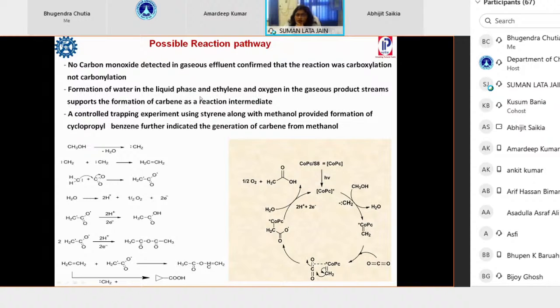Further, to confirm the formation of carbene, we used trapping experiments. We used styrene along with the methanol, and as expected, we got cyclopropyl benzene in the reaction. So these controlled experiments confirm the formation of carbene as the initial intermediate of the reaction. So by this, we propose the following mechanism.